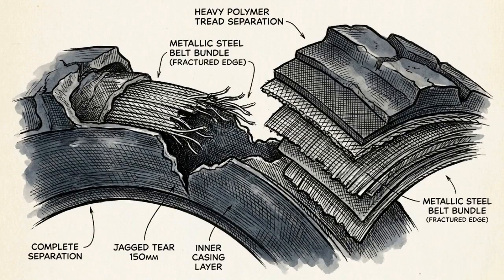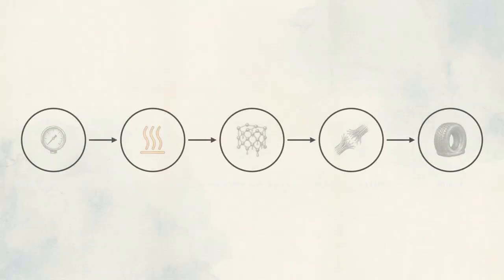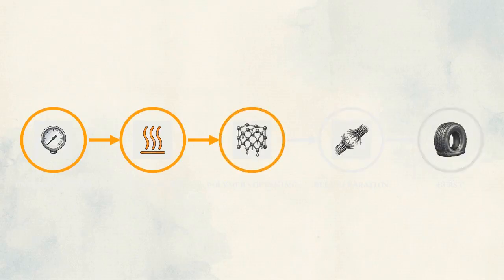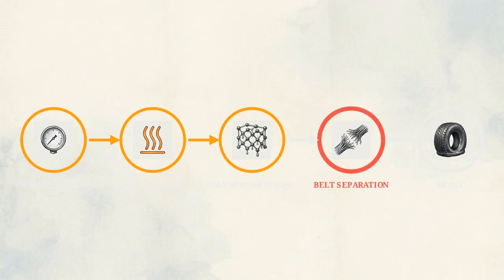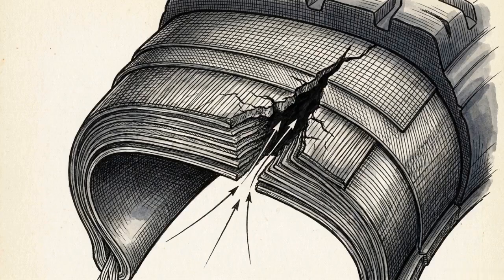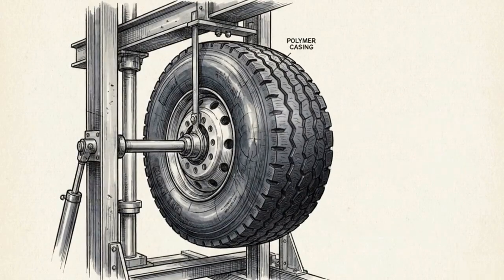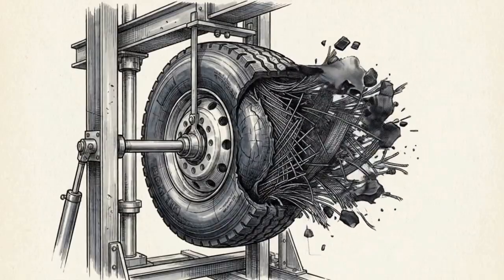This flowchart tracks the uninterrupted sequence. Underinflation triggers severe hysteresis and heat buildup, leading directly to polymer softening, belt separation, and a catastrophic burst. The terminal phase begins the moment the microscopic crack reaches macroscopic size, completely severing the steel belt from the casing edge. The 6.5 bar of highly pressurized internal air instantly floods into this newly formed structural void. The chemically degraded, melted sidewall has no capacity to contain this sudden internal pressure spike. The casing violently tears apart, resulting in the explosive rupture. The catastrophic blowout is the terminal outcome of a predictable, unmanaged thermodynamic loop.